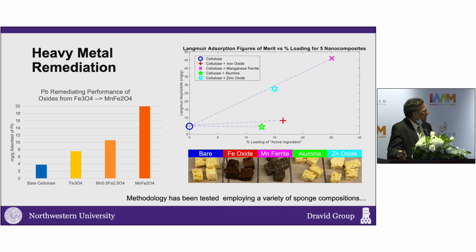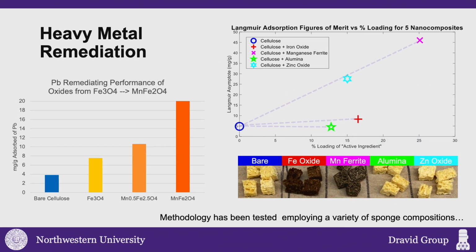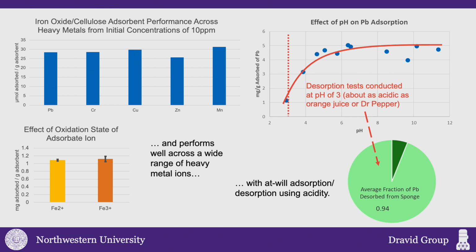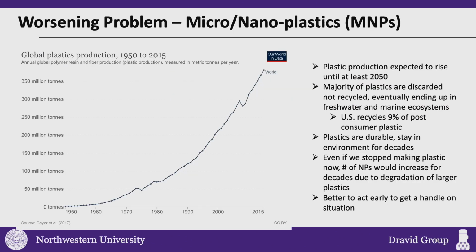So this is a second example of how we are now recovering phosphate using pH as the proxy. You can imagine now we are extending this to heavy metal. So there is a slight change in the coating. I know Sammy and others are doing this work, and we'll be happy to share our results and details. And what you see is, again, a pH-dependent sequestration approach. So we can not only capture lead in this particular case, but we can release it, almost 94%. And so you can reuse this. And again, reuse is the key for all the approaches that we are making.